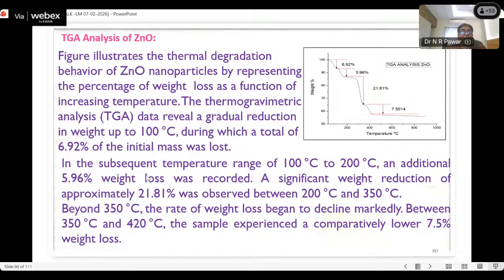In the subsequent temperature range, an additional 5.96% weight loss was recorded. A significant weight reduction of approximately 21.81% was observed in the temperature range from 200 degrees Celsius to 350 degrees Celsius. Beyond 350 degrees Celsius, the rate of weight loss began to decline markedly. Between 350 degrees Celsius and 420 degrees Celsius, the sample experienced a comparatively lower weight loss, that is 7.5% weight.